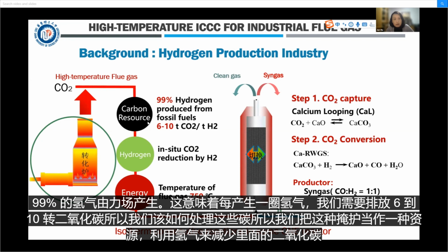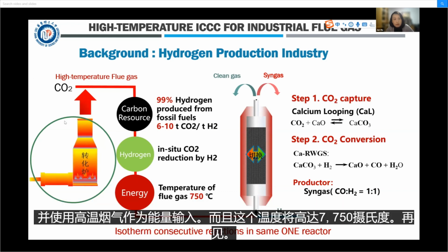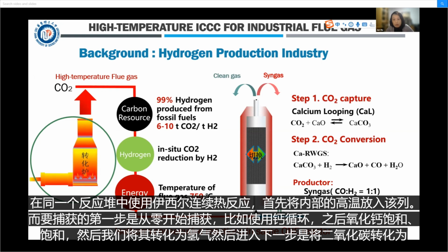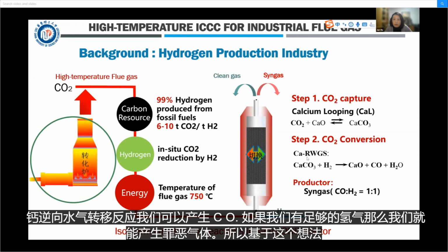So we take this carbon as a resource and use the hydrogen to reduce the CO2 in situ, using the high temperature flue gas as the energy input, and this temperature is as high as 750 degrees C. By using an isothermal consecutive reaction in the same reactor, first the high temperature gas goes into this column. The first step is CO2 capture, such as using calcium looping, and after the calcium oxide is saturated, we change to hydrogen, and then comes the next step, the CO2 conversion with the calcium-based reverse water gas shift reaction.